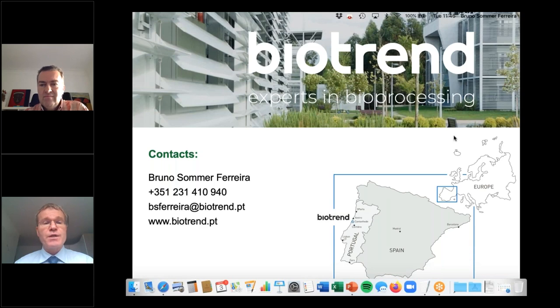Nevertheless, also in our hot pressing, as Bruno showed in some photos, depending on the application temperature, some of the samples which we produced with the hot press, which is quite aggressive in this context, were a little bit brown, but it's not like that in a real extrusion process, as Bruno was showing in the other photos from other products. So mainly it would be white, but there are also some light brown or colored things depending on the temperature during the processing.